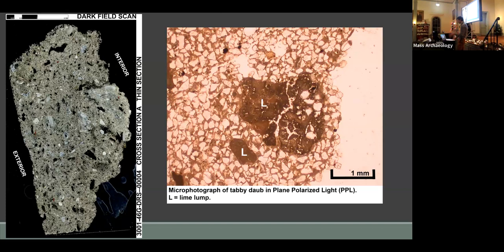Now, we can't see salt directly in thin sections, but a lot of shell fragments and sand grains do contain clay coatings depending on the sample, and that could indicate these materials came from a marine environment and were not well cleaned before being burned and then added to the mix. So the burning or calcining of oyster shells in a kiln or on a lime brick sets into motion a process called the lime cycle.